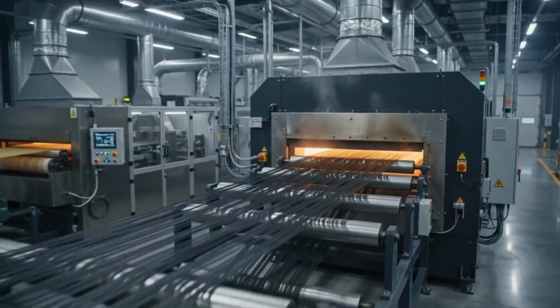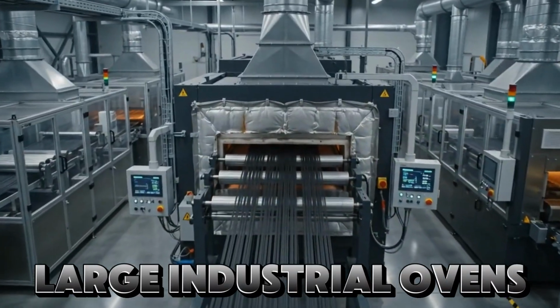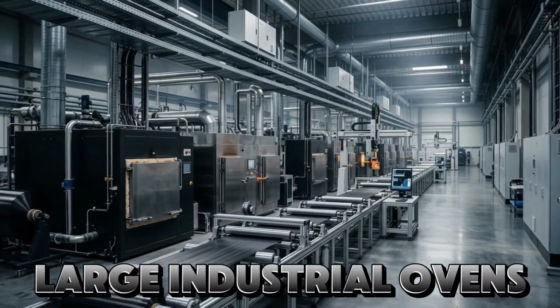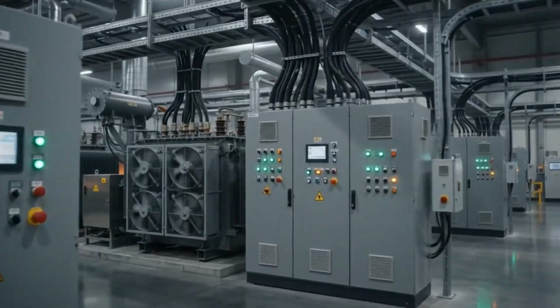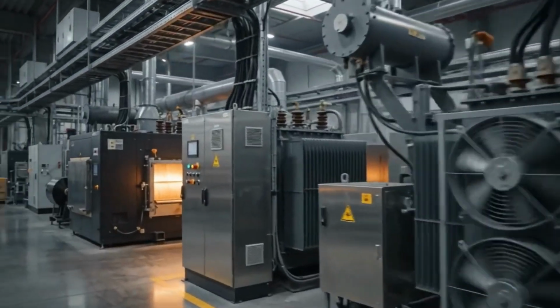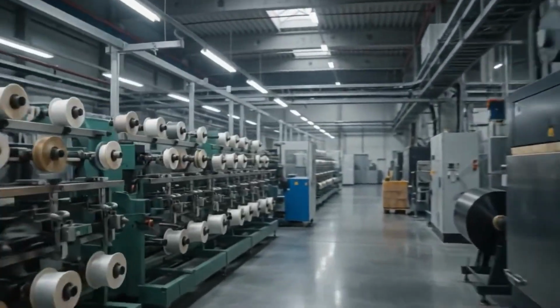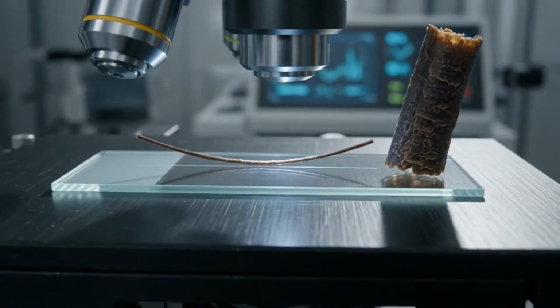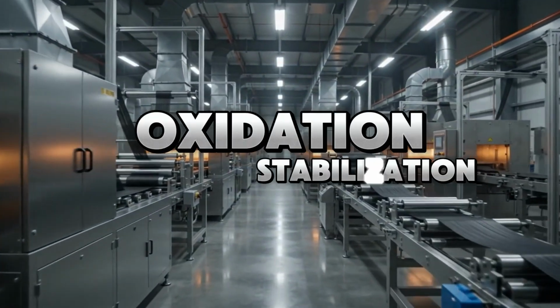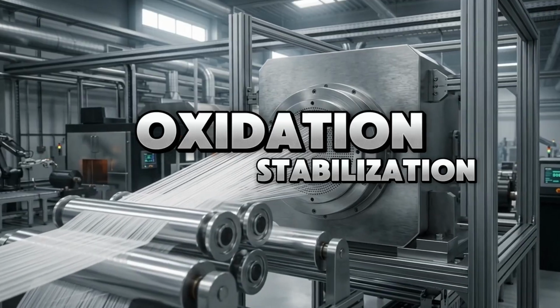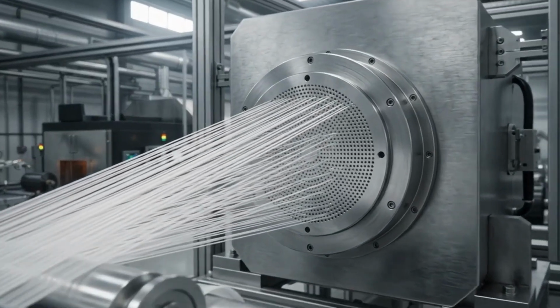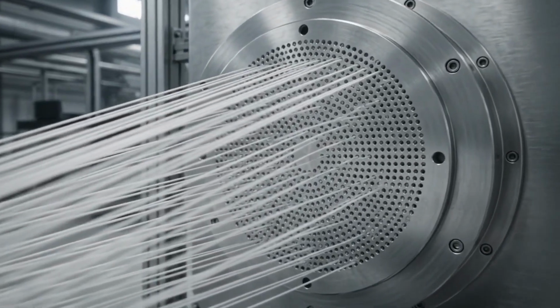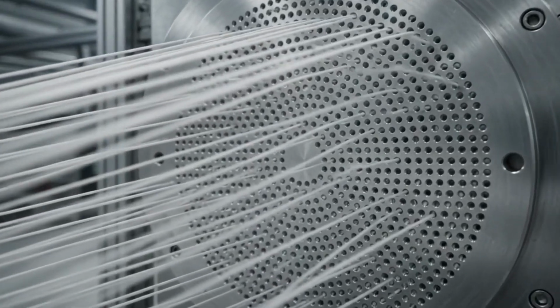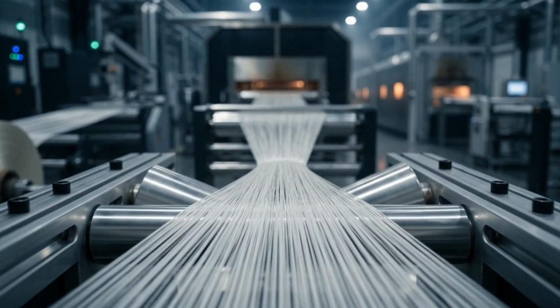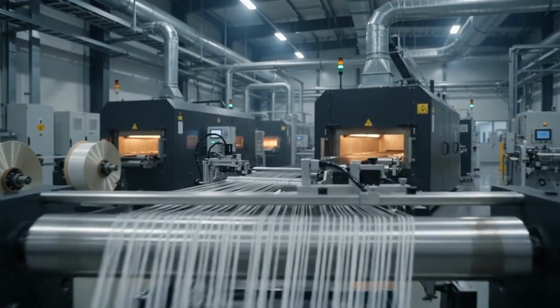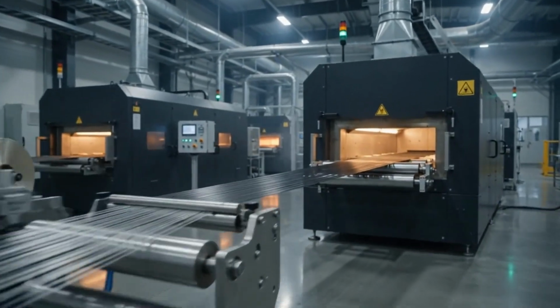The PAN fibers get fed into large industrial ovens, continuously under carefully controlled tension, and exposed to heated air at temperatures between 200 and 300 degrees Celsius, and they stay there for hours. This process is called oxidation or stabilization. What it's doing chemically is rearranging the molecular structure of the PAN, converting straight polymer chains into a more complex, ladder-like structure that can survive what comes next. Without this stage, the fibers would simply burn up in the next furnace rather than transforming into carbon fiber.